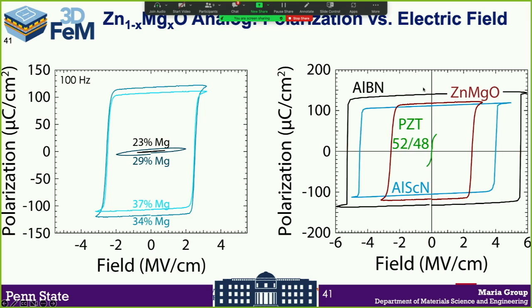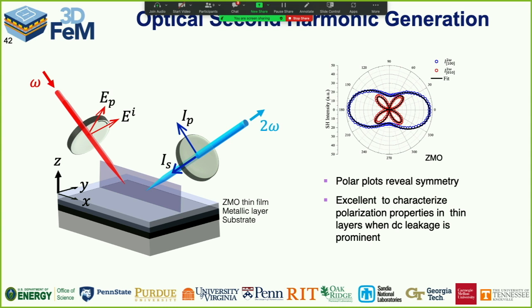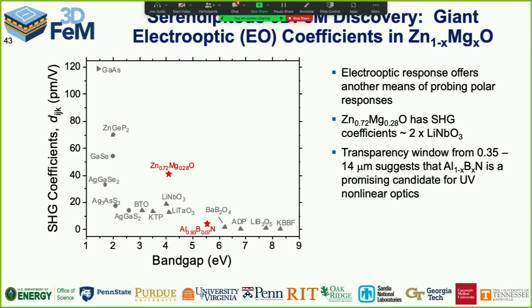So we lose a little bit in terms of polarization. These materials are typically closer to 80 microcoulombs per centimeter squared than 125 microcoulombs per centimeter squared. And completely serendipitously, we were using second harmonic generation to look at the domain states in these materials. This is work of Professor Venkat Gopalan, and he does SHG polarimetry and found out that these materials have really, really big second harmonic generation coefficients.